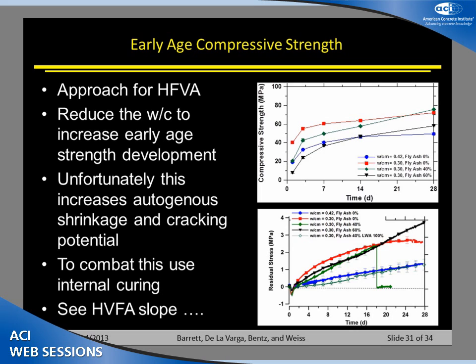So over here we've got our 0.42 water to cement ratio concrete. If we just dropped the water to cement ratio and did nothing else, we would get this red line with the stresses really building up inside the concrete that could lead to cracking. Right? If we just have the high volume fly ash in the system, we again would see high stresses, and one of the differences is because we're reacting more of the cement, we would see these higher stresses going for a longer and longer period of time.